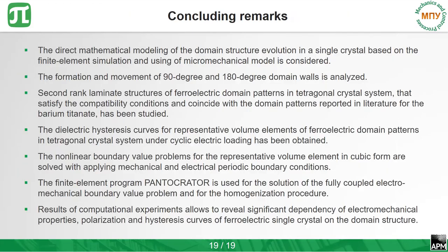So yeah, that's all, concluding remarks, summing up. A direct mathematical model of the domain structure evolution in a single crystal, based on the finite element simulation and using the micromechanical model, is considered. The formation and movement of 90 and 180 degree domain walls is analyzed. Second rank laminate structures of ferroelectric domain patterns in tetragonal crystal system that satisfy the compatibility condition and coincide with the domain patterns reported in the literature for barium titanate have been studied. The dielectric hysteresis for representative volume elements of ferroelectric domain patterns has been obtained, and the nonlinear boundary value problem was solved as well. The finite element program is used for the solution of the fully coupled electromechanical boundary value problem and for the homogenization procedure.